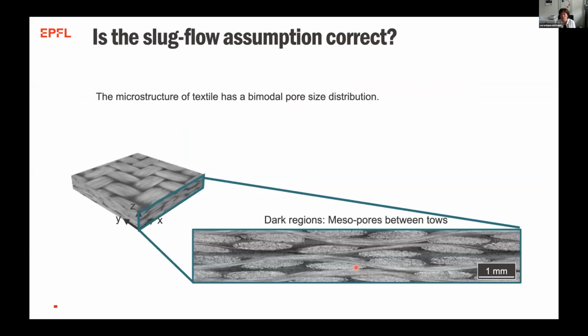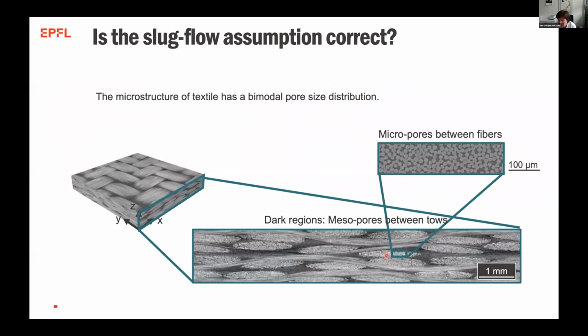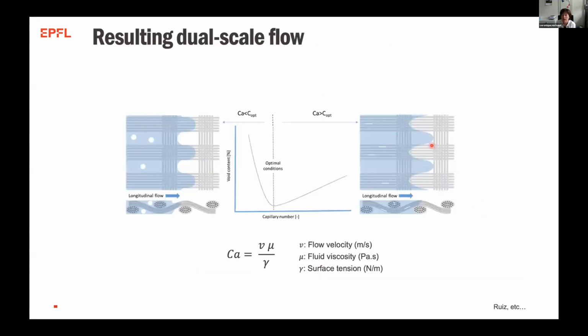So it's linked to the bimodal pore size distribution, and any fabric has it. And you see that you have a lot of dark areas, which are big pores. And then you have micropores in between the fibers, with super high volume fraction regions. So when you're impregnating, the flow will want to go, depending on many things, either in the big spaces or in the micropores between the fibers. This has been seen now by many people. I didn't have time to put all the references, but you can find them or ask me. It's the result of the dual scale nature of the fabrics.